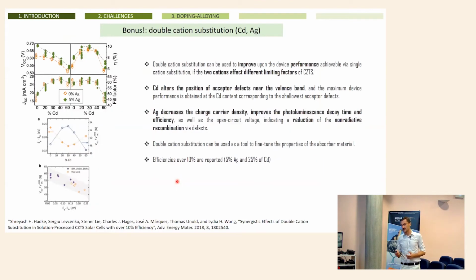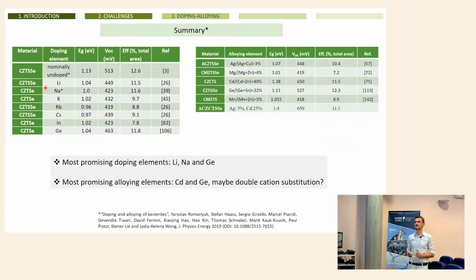And as a bonus, recently some groups started to work on co-doping, on double cationic substitution, for example, using cadmium and silver with very interesting results. We are now working on double substitution with germanium and lithium, also trying to improve the properties of this material.